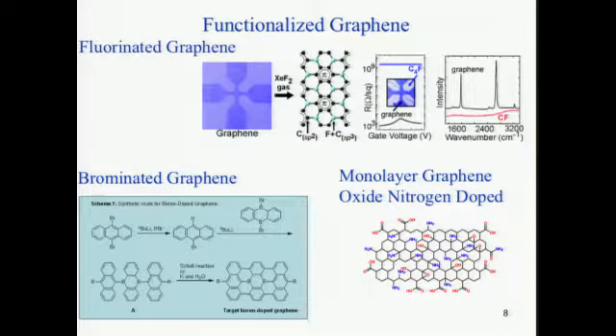because you no longer have the sp2 bonding. And in brominated graphene, you can think of similarly, when you brominate, you actually replace a carbon with a bromine. And that's not what we're looking for. We want to functionalize it, but we still want the good properties of graphene at the same time. And some other ways that people are looking at is using monolayer graphene oxide and by nitrogen doping it. And that's interesting because without the graphene oxide, you can't really functionalize graphene.